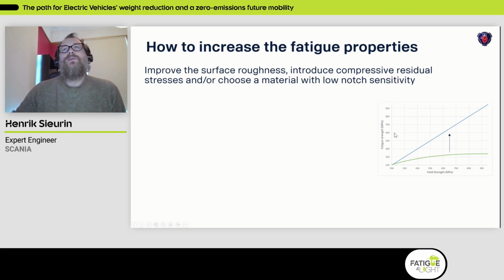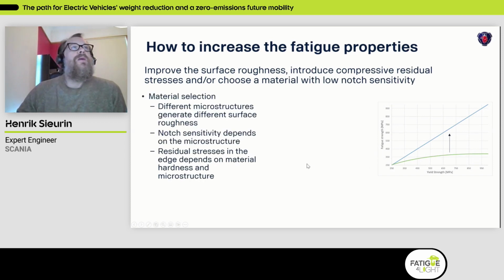But of course, if you still want to increase the fatigue strength, what do you do then? Either you have to work with the surface roughness, or you can introduce compressive residual stresses, or even choose a material with a lower notch sensitivity. Working with the material, different microstructures first of all generate different surface roughness if you machine it or punch it, for example. A ferritic-pearlitic material generally gives a rather rough surface with a bad surface roughness. On the other hand, if you have a pure martensitic steel, you get more like a cleavage fracture with a better surface roughness. And then also the notch sensitivity actually depends on the microstructure.